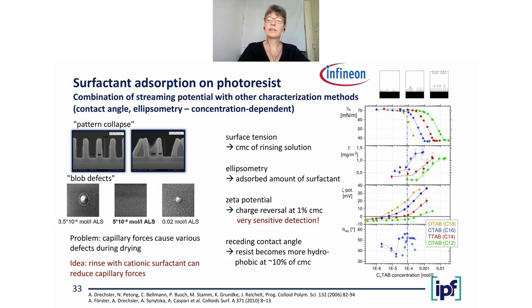This is a slightly older example. This was a work we did for the microelectronic industry for Infineon. The guys had very big problems in the photolithography due to capillary forces during the drying after the development of the photoresist structures. Sometimes the photoresist structures collapsed during the drying. Sometimes remainders of the photoresist remained on the wafers and caused defects. And it was clear that this was an effect of capillary forces, and that's why we tried to find a method to reduce the capillary forces.